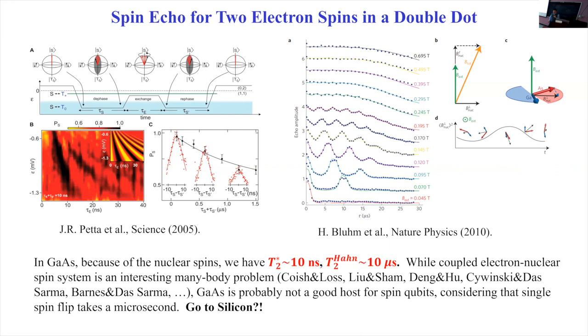So from the electron spin perspective, these randomly distributed nuclear spins give you an effective random magnetic environment. Now, if there's no dynamics, which is sort of true, the nuclear spins do evolve slowly on the time scale that the electron spins have dynamics. But still, there are dynamics, right? There is the dipole coupling between nuclear spins, there is the electron-mediated nuclear spin couplings, etc. So with dynamics in that reservoir, in that magnetic environment, that limits the coherence property